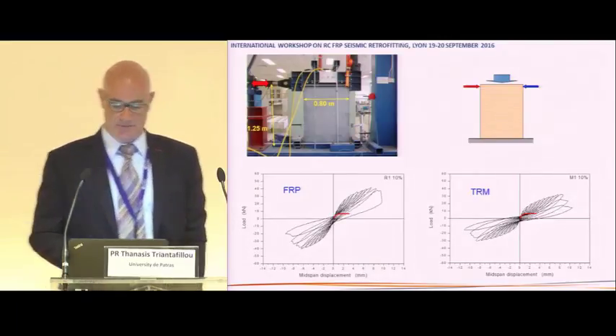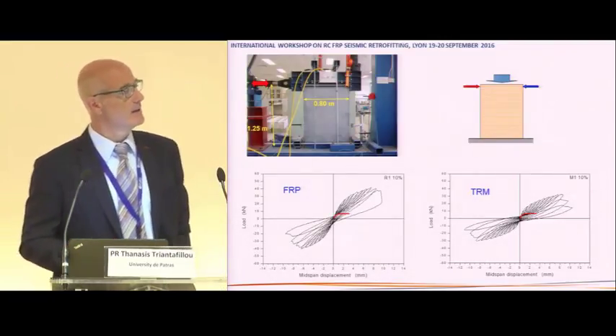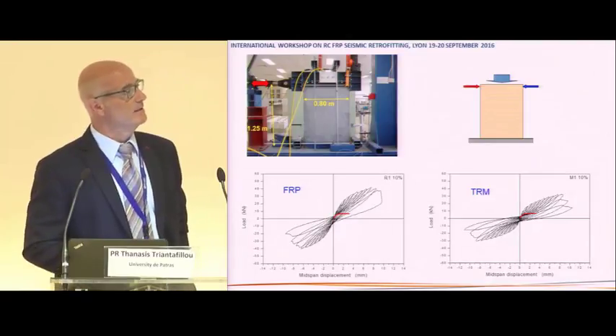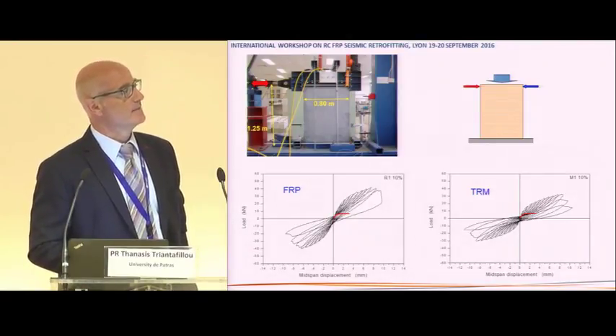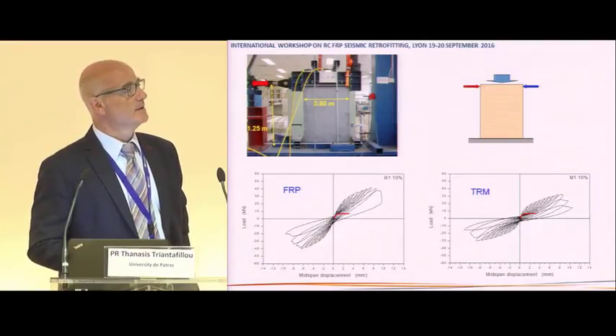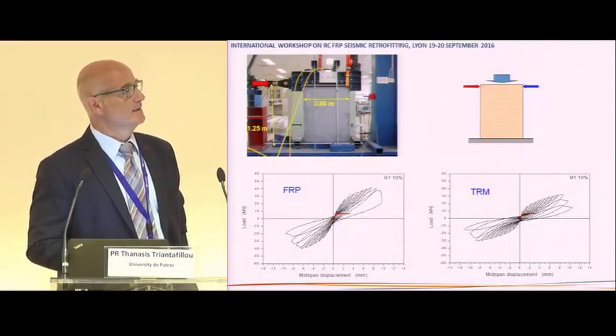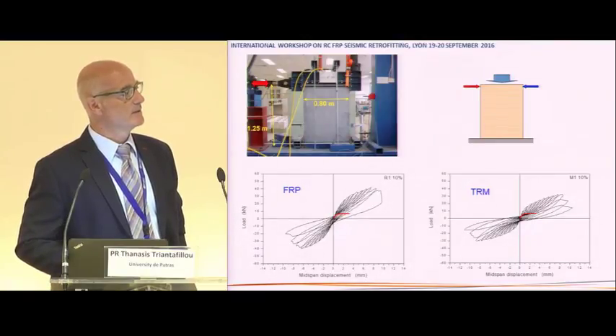A few examples of why it works well in comparison to FRP. If you take, for instance, a masonry wall subjected to in-plane loading combined with axial force without any retrofitting, the response would have been what you see by the red line here at the bottom. If you look at load versus displacement, the response is what you get by the red line.